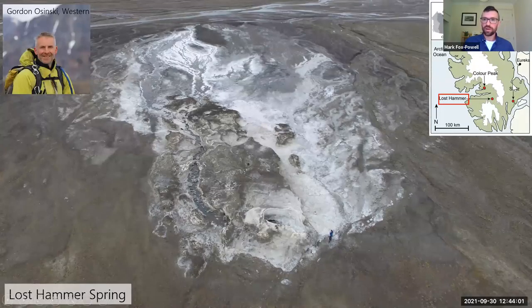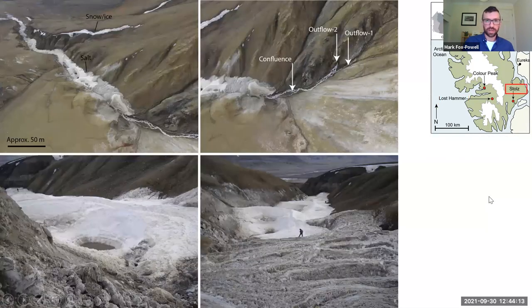We visited three springs you can see on the map. Lost Hammer Spring, which is another shot of the same spring in the background here, and Stolz Spring on the eastern side as well. I'll just show a quick picture of that. It's on a completely different scale. Here we're looking at a kilometer-sized deposit that fills an entire ravine. You can get a sense of scale by one of our field team stood on the deposit. And this is slightly different. This is a very chloride-rich, again hydrated salts, but it really is a glacier-sized salt deposit forming here.